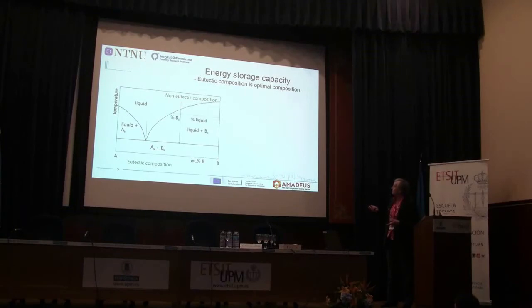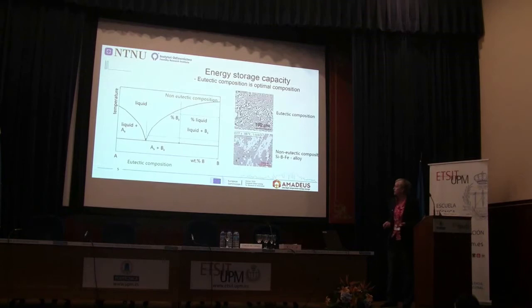So here we will have some solid, some liquid. If we go to an even lower temperature, we will have more solid and less liquid, which means that when we finally come to the solidification temperature, our phase change material will actually only have 50% liquid left, right? Which means that we only get back 50% of the latent heat. So it means that we don't want to be at a non-eutectic composition, we want to be at a eutectic composition. So that is one of the strategies that we have had in the Amadeus project.